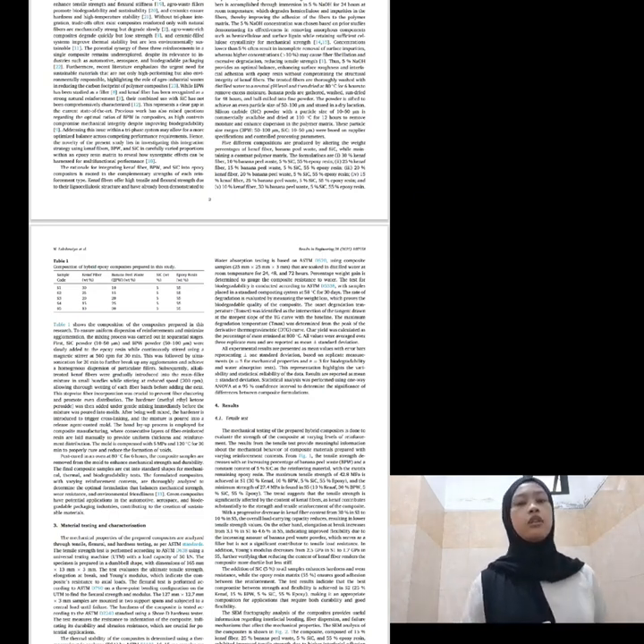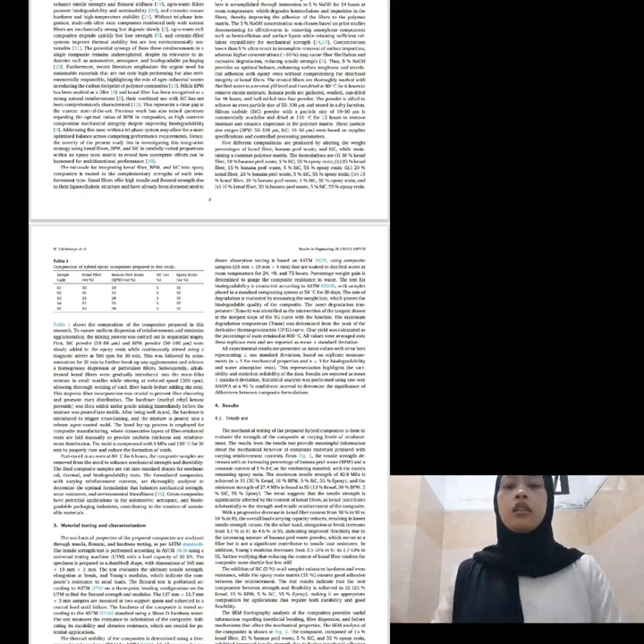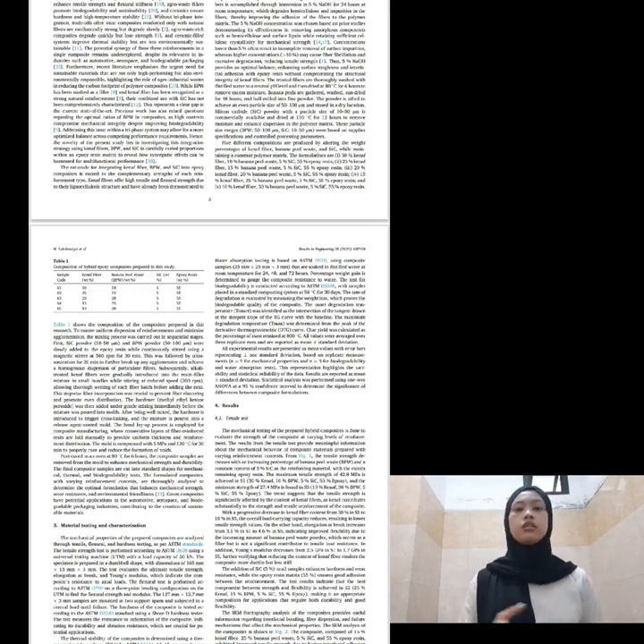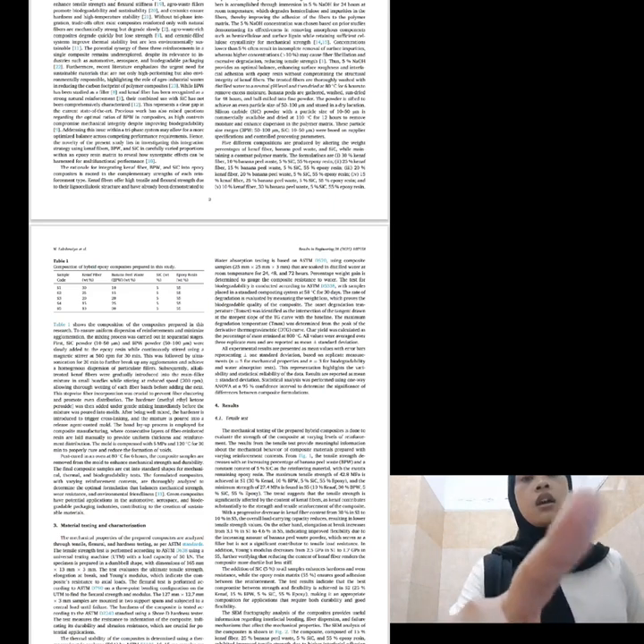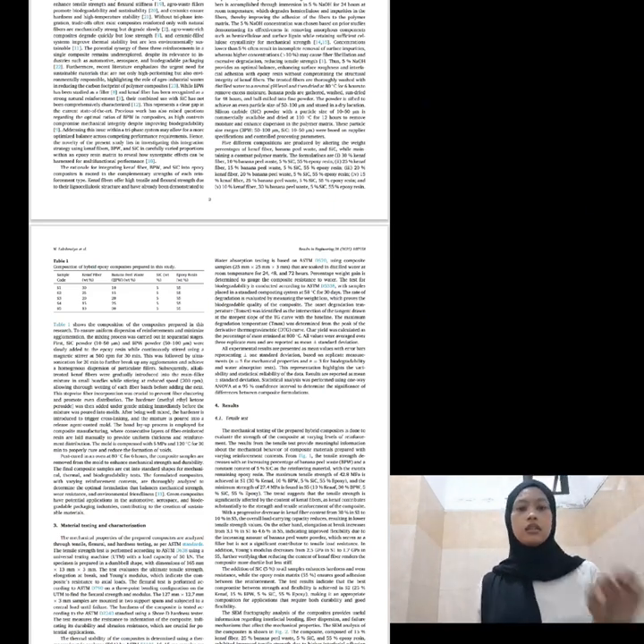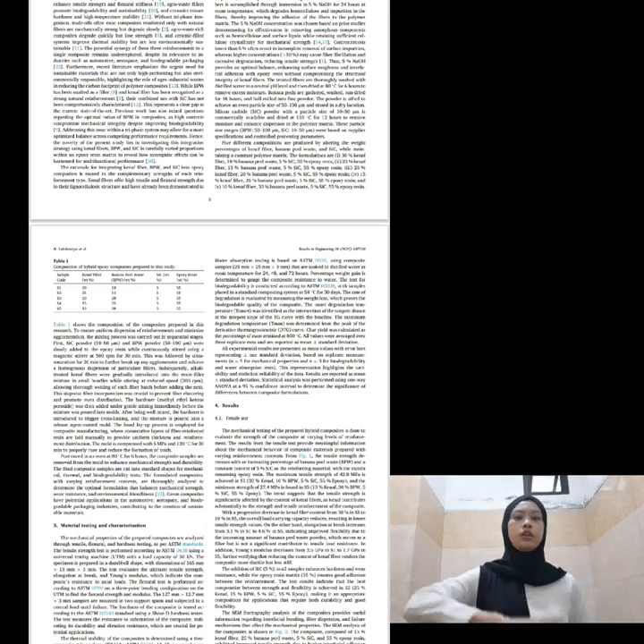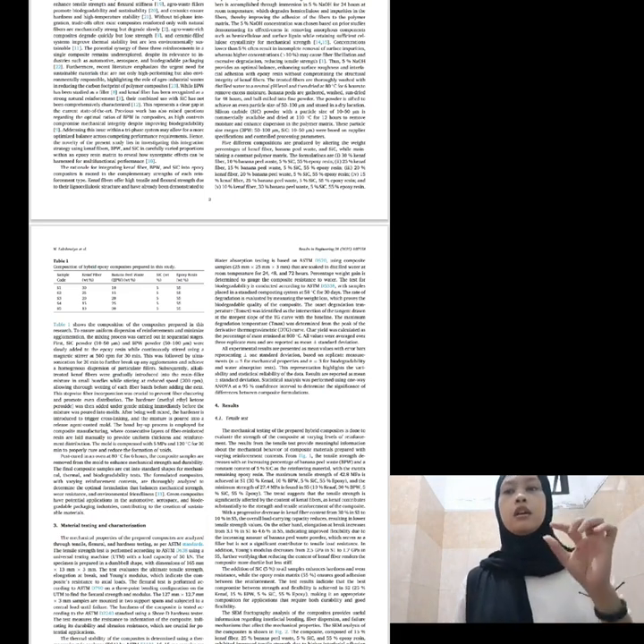First, kenaf fibers were treated with 5% NaOH to remove impurities and improve bonding. Second, banana peels were dried and cut into 50 to 100 μm powder, and 10 to 50 μm was pre-dried. Third, 5 composite formulations were made by varying kenaf and BPW content from 10 to 30% while keeping 5% SiC constant. Mixing was done using stirring and ultrasonication for uniform dispersion. Composites were fabricated by hand layup and hot pressing at 120 Celsius, 5 MPa, 30 minutes, then oven cured at 80 Celsius for 6 hours.